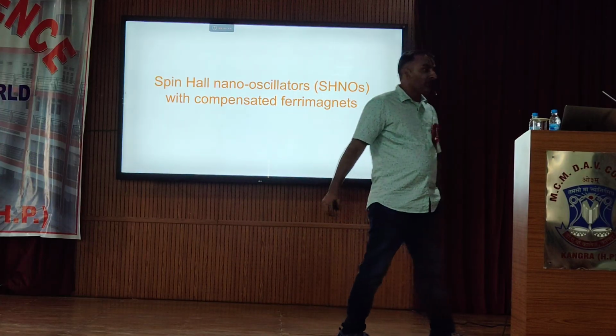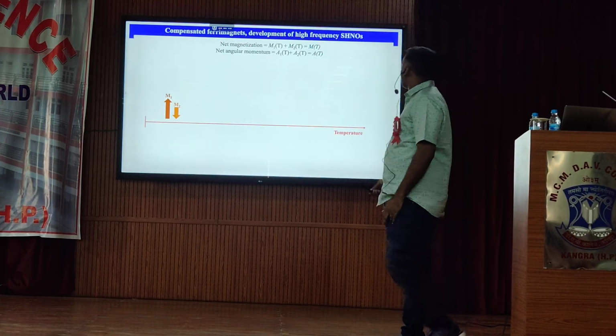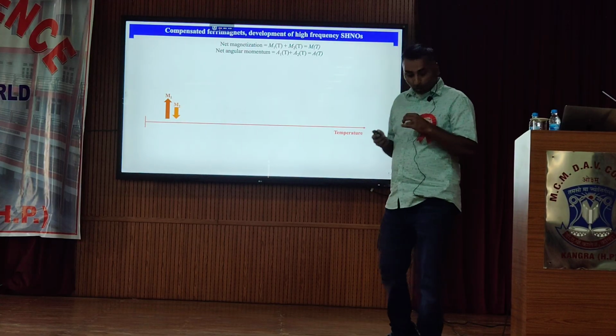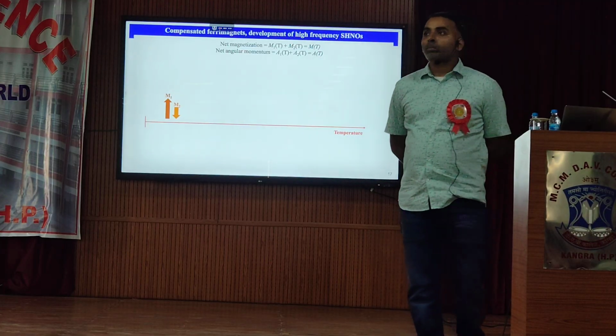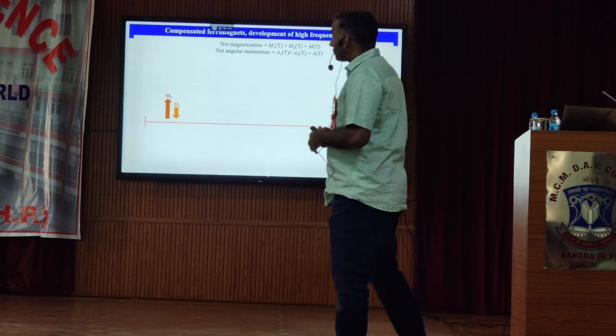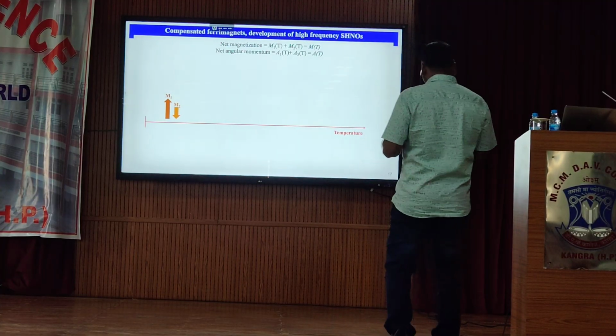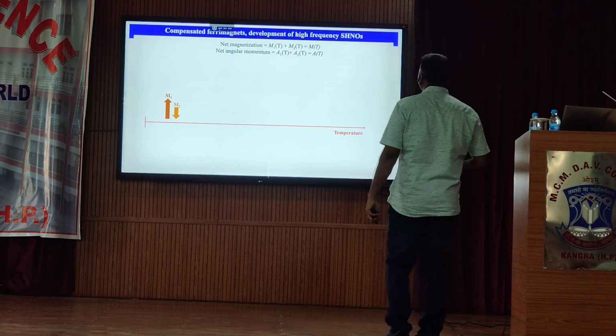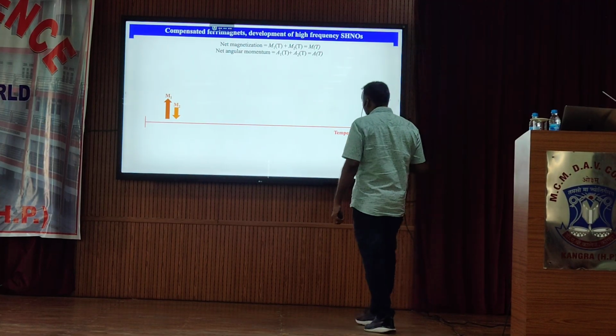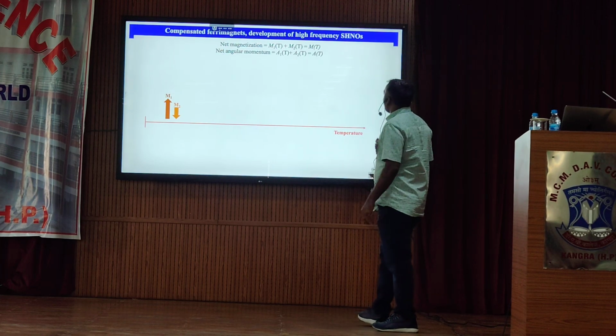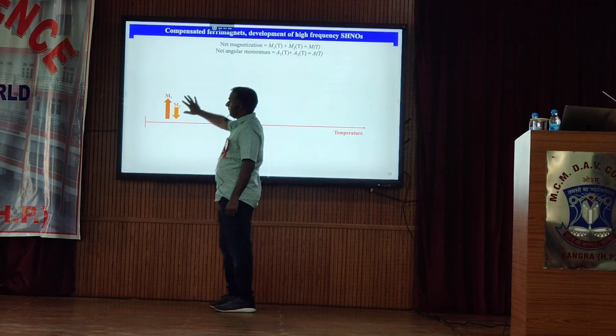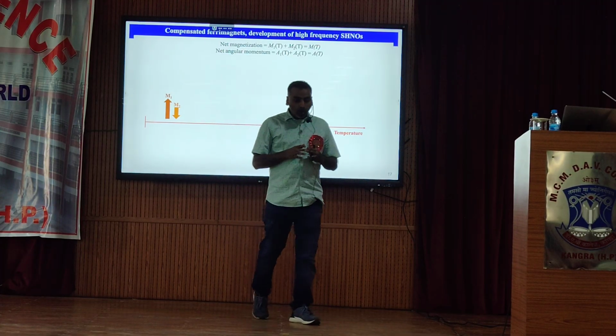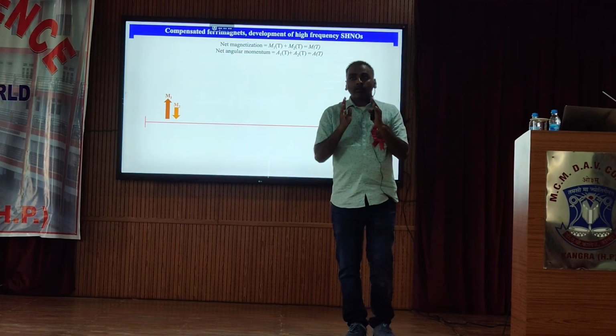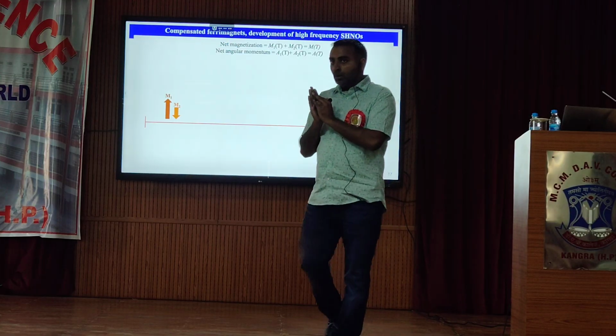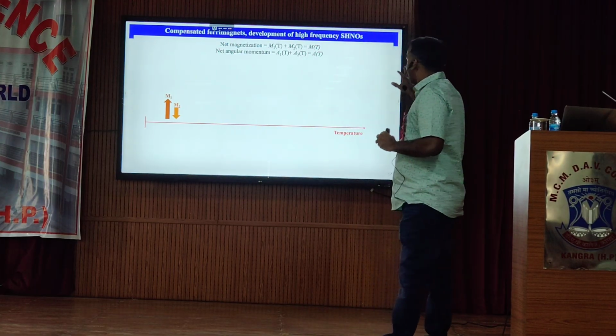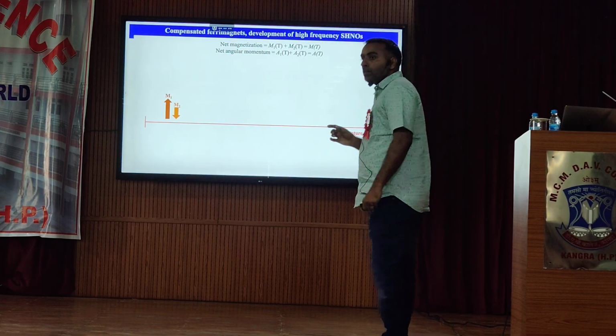Since compensated ferrimagnets have two sublattices, I will first introduce what a compensated ferrimagnet is. If you have done the course on condensed matter physics, you might have gone through it. In ferrimagnets, we have two magnetic sublattices, M1 and M2, and the net magnetization is nonzero because we have unequal sublattices, which is different from antiferromagnets. In antiferromagnets, we have two sublattices that are equal and opposite, so the net magnetization is 0. But in ferrimagnets, we have a nonvanishing net magnetization because the sublattices are unequal, so we remain with some net magnetization value.